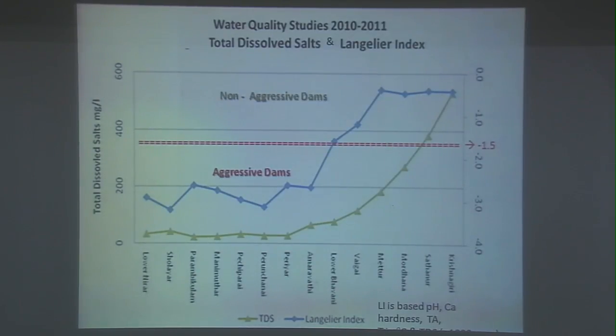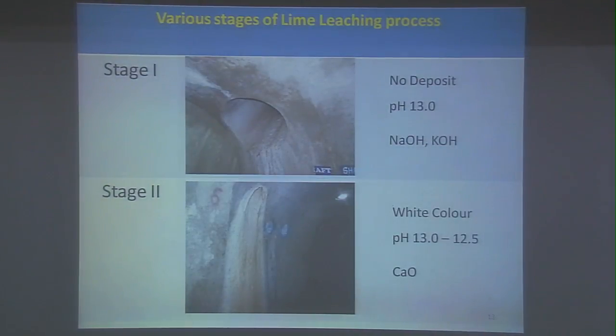We have already seen the dams with soft waters, that is, with low pH and low TDS. They are more aggressive dams: Amaravathi, Periyar, Pechiparai, Perunchani, Manimuthar, Parambikulam, Sholayar and Lower Neeraar. And of course, the lime leaching process is a complex phenomenon. We have tried to explain this lime leaching process in 6 stages based on our past experience and theories. You can see stage 1. Here in this stage, normally the water stored in dams will seep through the dam and be collected in the drainage gallery.